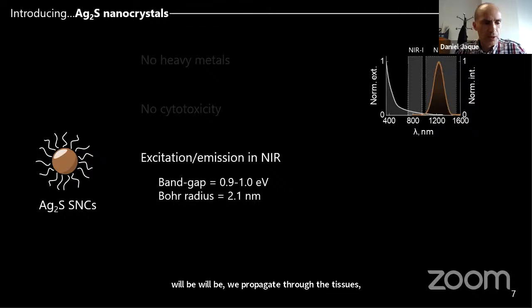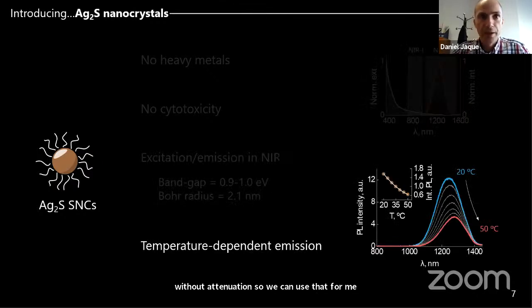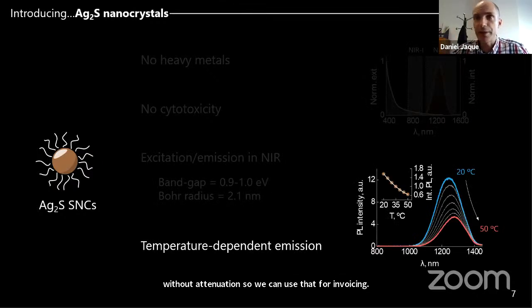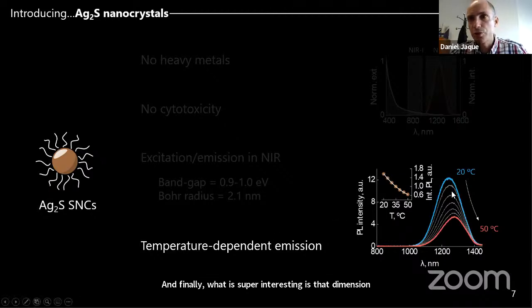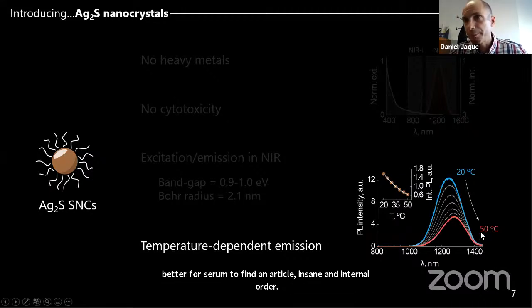So we can use that for in vivo imaging. And finally, what is super interesting is that the emission properties of these nanoparticles are super temperature dependent. So you are able to measure the emission spectra for silver sulfide nanoparticles inside an internal organ. You can see that the emission spectra depends on temperature.